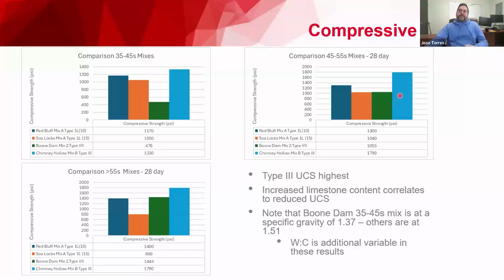At 45 to 55, again type 3 is the winner there—not the winner, but just the highest strength, if you care. Looks like 1L and 1-2 performed pretty similarly.